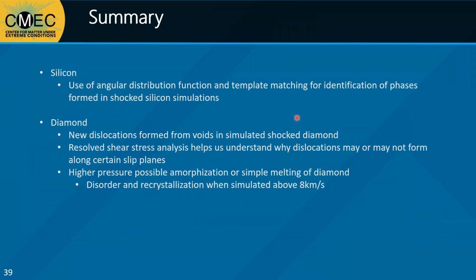In summary, we use the angular distribution function in shocked silicon to help identify transformed silicon phases. And in shocked diamond, we found a strong orientation dependence in the threshold for dislocation formation, as well as performing resolved shear stress analysis to help explain why some dislocations were not present. Additionally, high pressure simulations found disordered and recrystallized diamond when going above 8 kilometers per second for the Tersoff potential.